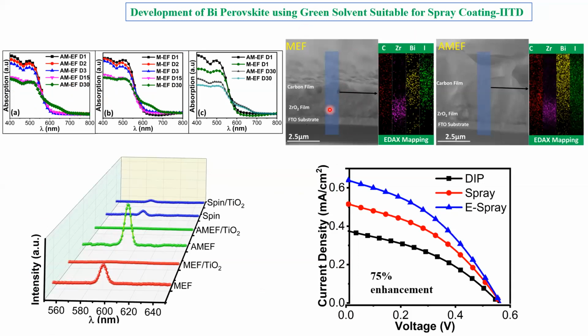These are some EDAX mappings, which I showed you earlier also. We see that bismuth is getting very much infiltrated, and the density of the material is very, very high when we use this protocol in the spray coating methodology. And these are some efficiencies. Efficiency is not that good for bismuth perovskite as of now, but still we are getting very good voltage. Overall, as the infiltration is more, we can get good PL quenching. PL shows that whatever electrons are forming go directly to the TiO2. We got really very good quenching.